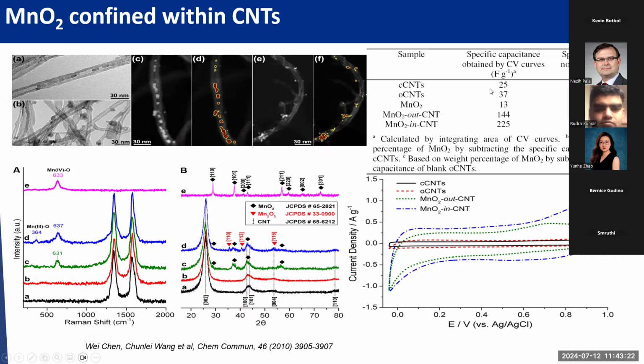So you can see for the closed tip nanotubes without any treatment, we only get 25 Farad per gram. And that's from the CV, from the cyclic voltammetry results. So you can see the black line in the CV curve. This is the closed tip carbon nanotube. And if we open the tips, then more electrolyte can penetrate into the carbon nanotube. Then we have a little bit of increase of the specific capacitance up to 37 Farad per gram.